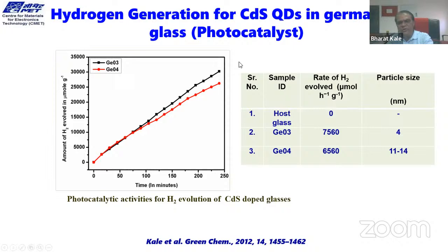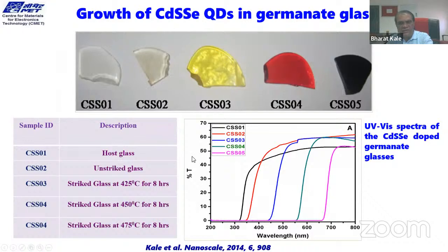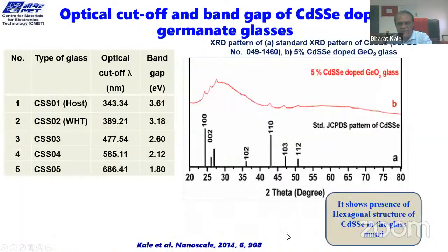So then we use it for hydrogen. Much more enhanced hydrogen is observed with this glass. Then we also use CdSe. You see the band absorption spectrum from 300 to 700 with the size effect. Again, it is a size effect. With the size in the same glass, we can have all kinds of colors. Initially, this black glass is a transparent glass, though it shows black because of quantum dots. You see, it is almost 60% transmittance.